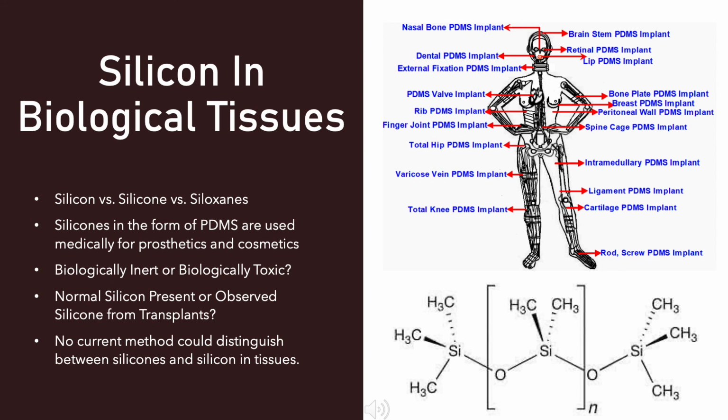It was mainly made up of silicon and oxygen alternating bonds that have methyl groups attached to them. These methyl groups can be substituted by other groups, allowing organic groups to attach to inorganic groups. The silicones make PDMS thermally and chemically stable, along with being transparent, permeable, and hyperelastic. This allows them to be good candidates for prosthetics and cosmetics.